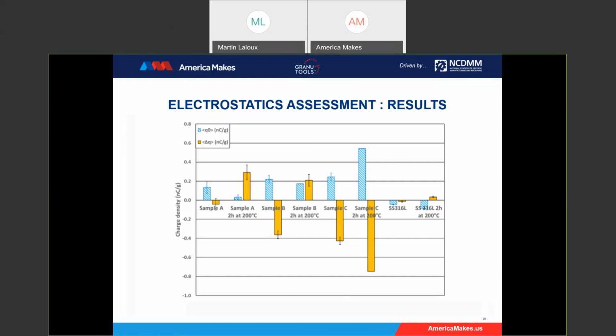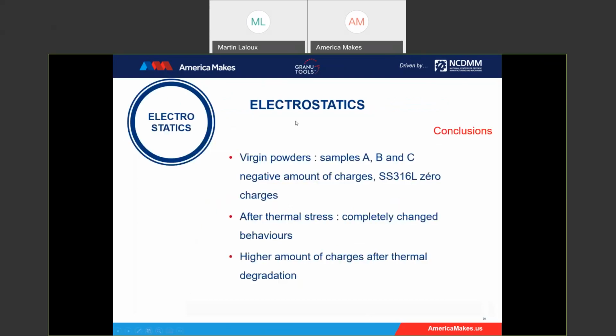After a flow through the pipes, sample A acquires the lowest amount of charge in comparison with B and C. And after the thermal stress of 200 degrees, the powder behavior is highly interesting. For example, for A and B, the initial charge decreases, and the final charge changes from negative to positive. For C, the trend is conserved. Stainless steel is slightly impacted and becomes positive. So the conclusion on the electrostatic charge: the virgin powders, samples A, B, and C, have a negative amount of charge. The stainless steel acquires almost zero charge because it's against stainless steel. The behavior is highly interesting and changes after the thermal stress.